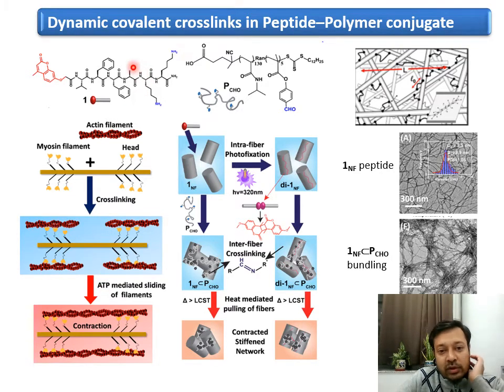So what we did is that we took our material which has a coumarin unit on it, which, as you know, can also photodimerize to make a photofixated sample. And we also took a very interesting functional polymer, polyNIPAM. Now polyNIPAM, as we know, because of its LCST, lower critical solution temperature, collapses above that temperature, and because of this collapse it can give very interesting thermoresponsive properties. We also have a copolymer which has some aldehyde that can form a very nice Schiff base with this lysine unit.